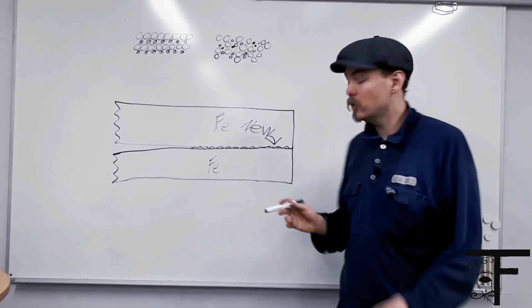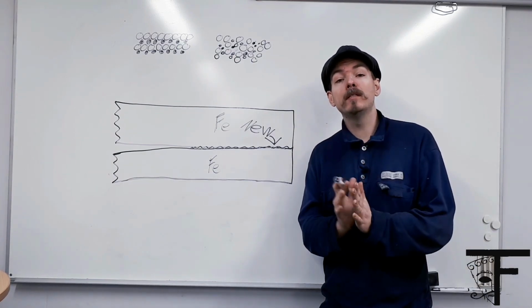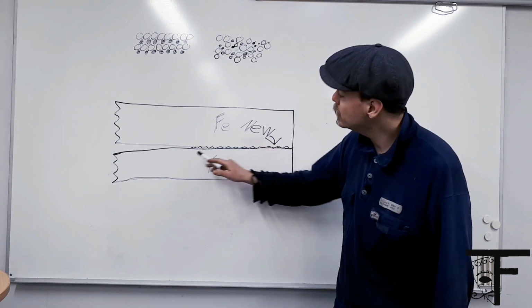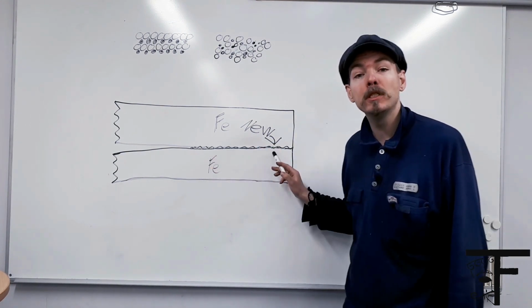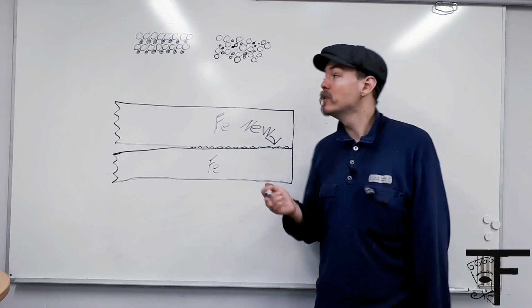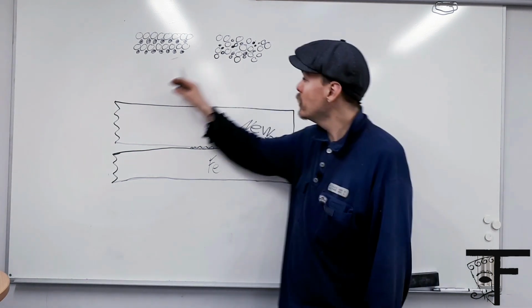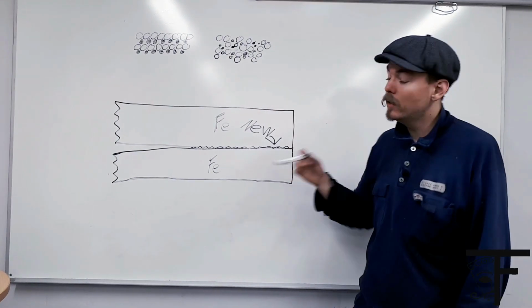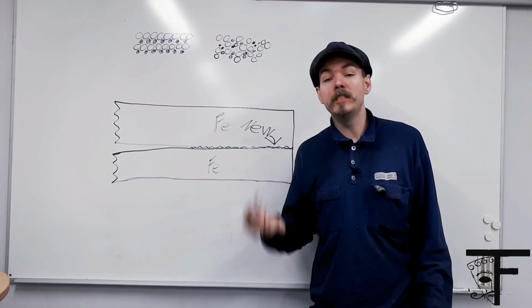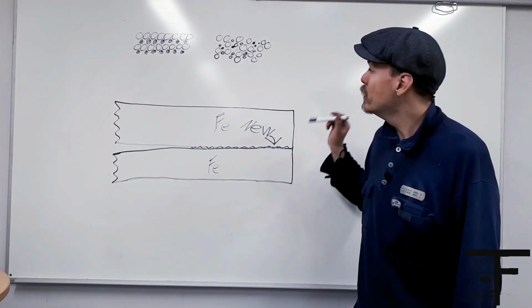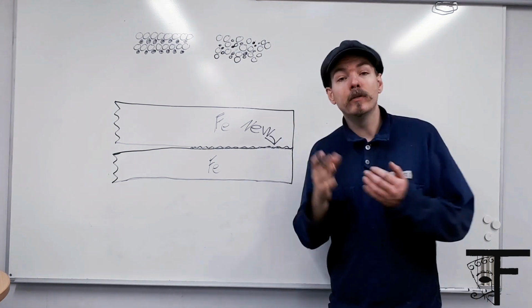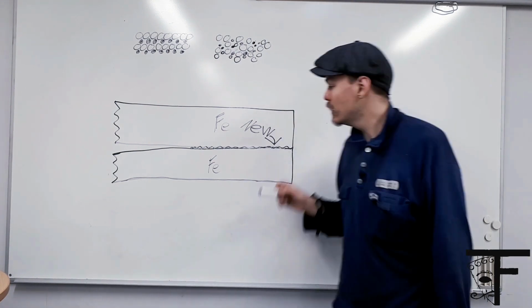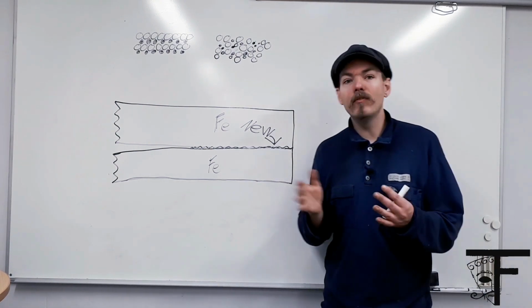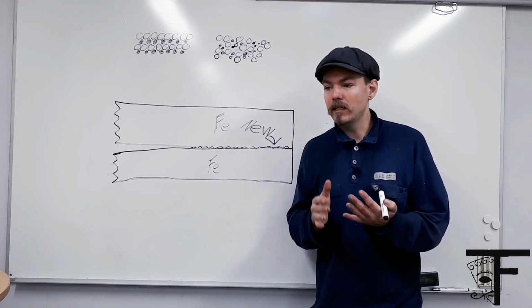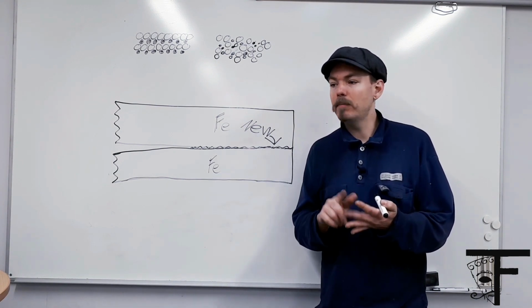So when the piece is welded together into one solid object, it's still not homogeneous because you create a new compound, which is the diffusion line, and that is a new material. So even though I did start with iron, you create something new in between, because it absorbs and rejects different materials, which has a completely different crystallization and atom structure. And you can see it in the form of veins. So you can see it in wrought iron, Lancashire, pattern welding.